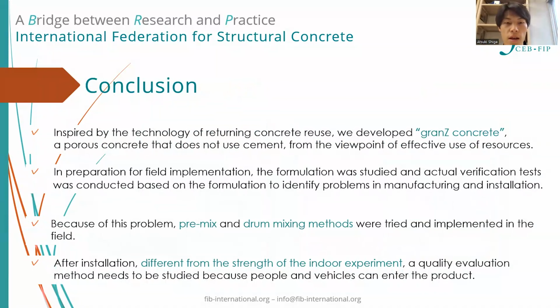In conclusion, taking a hint from granulation technology, an effective method of using return concrete was developed and applied to granZ concrete, a new form of cementless porous concrete that uses waste materials. Compressive strength tests were conducted, and the results show lower strength compared to ordinary concrete. However, it is possible to ride on it from the next day at the actual site, and it is expected that the difference can be reduced by taking into consideration the curing effect and other factors.